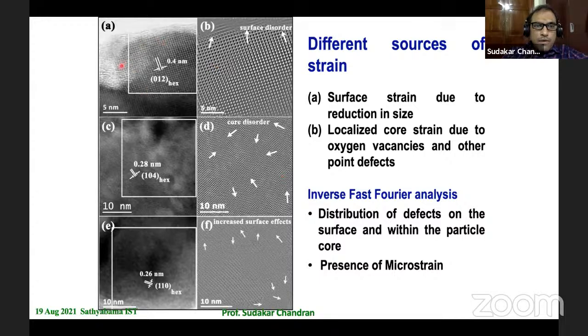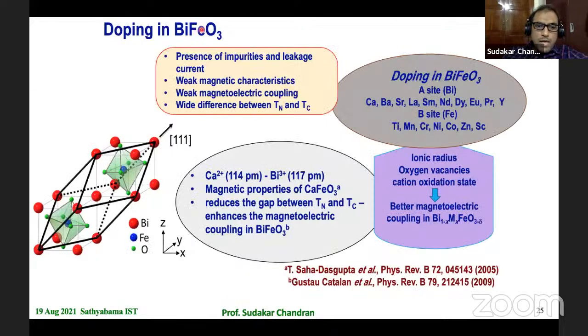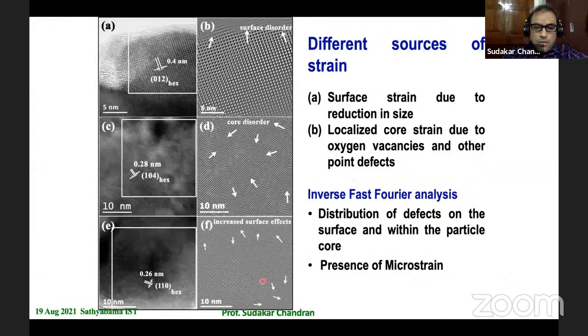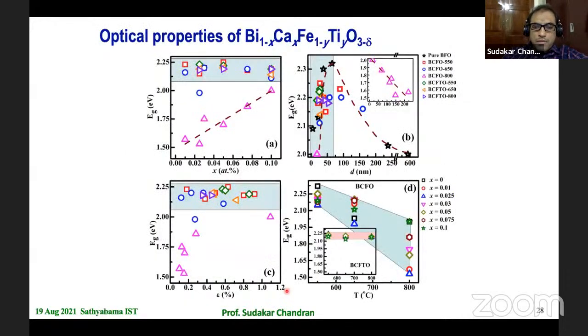In the pure case, you do have defects on the surface, as has been pointed out here. But in the calcium doped cases, where oxygen vacancies get introduced even within the crystal lattice, the core of the crystals, you can see a lot of distortions coming up. One can also minimize that by co-substituting titanium. Okay, so bismuth 3 plus and calcium 2 plus, the one charge difference is compensated by Fe3 plus and titanium 4 plus. So equimolar substitution of calcium and titanium seems to get rid of the core defect states, but again the surface defect states are prevailing, and the titanium doping also introduces the size reduction.